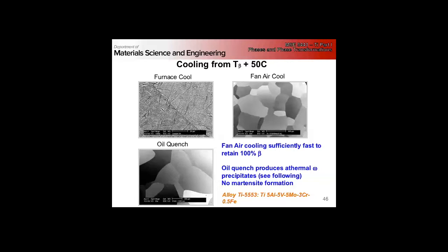If we force air cool or oil quench, we retain a fully beta microstructure. You can't see it, but oil quench is fast enough to produce athermal omega, right? So it's almost like martensite because it's athermal, but it's the omega phase. It's not the martensite phase.